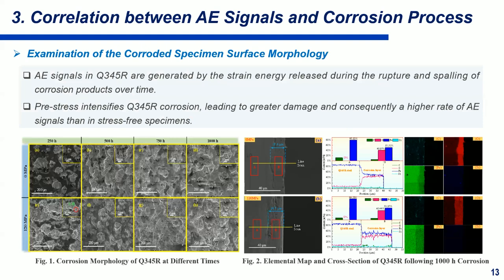When we check the morphology of the corroded specimen surface, AE signals in Q345R are generated by the strain energy released during the rupture and spalling of the corrosion products over time. Pre-stress intensifies Q345R corrosion, leading to greater damage and consequently a higher rate of AE signals than in stress-free specimens.